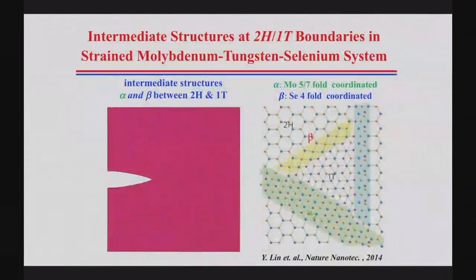Okay, and then it turns out there are some very interesting intermediate structures that experimentalists have discovered using electron microscopy. This is again the same material, and there are intermediate structures which are called alpha and beta. Beta is shown over here, and in the beta structure, the selenium atom, which is usually coordinated, that is, joined by 3 molybdenum atoms, is in this case joined by 4 atoms.